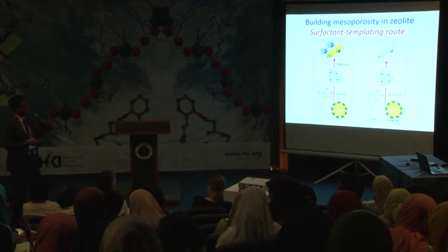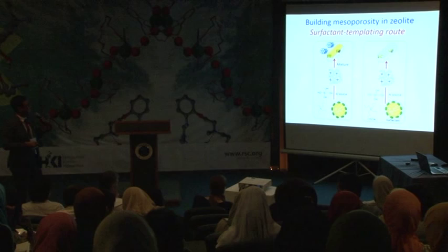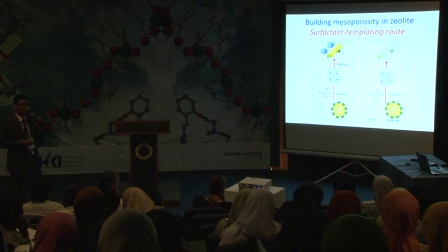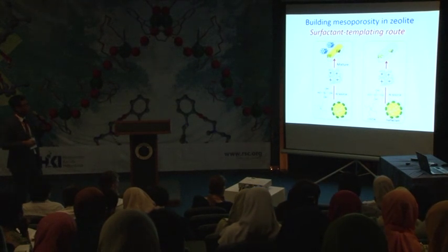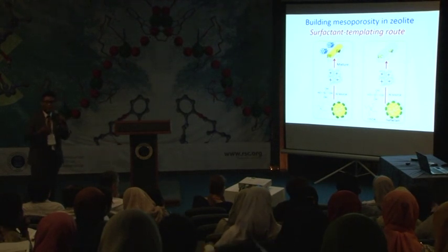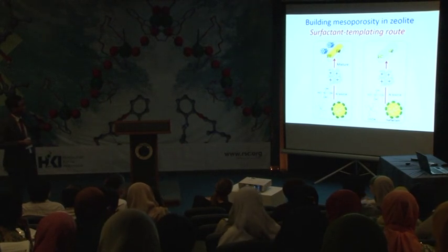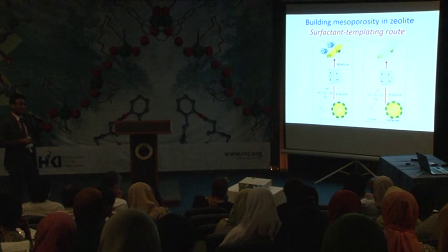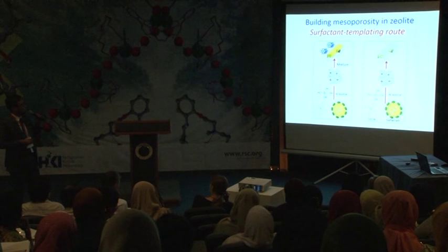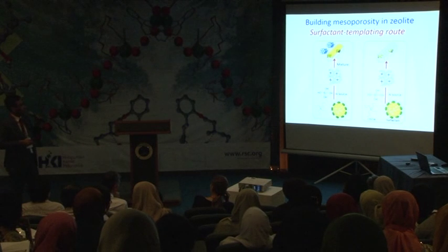We were interested in synthesizing with this bottom-up approach with the surfactant templating route. But the problem with this surfactant templating route is that we could get such a physical mixture in the end. We are expecting to get this zeolite with hierarchical porosity in one system, I mean in one crystal morphology, but in the end, if we are careless, we could get two materials, somewhat mixing the mesoporous material with the mesoporosity and the normal zeolite. So this is the disadvantage of this surfactant templating route.